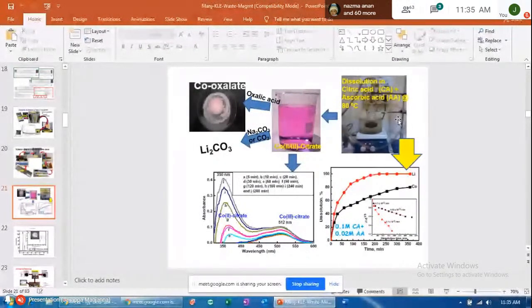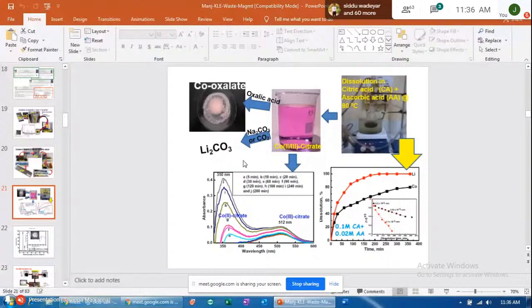We can check how this complexation takes place and what the dissolution rate is. All these things we collect data for our publication purpose. Now, once such a dissolution is over, then we precipitate it. We precipitate cobalt as cobalt oxalate, and lithium as lithium carbonate. Simply by purging carbon dioxide, it is possible to precipitate lithium as lithium carbonate, and by putting oxalic acid, I get cobalt oxalate.